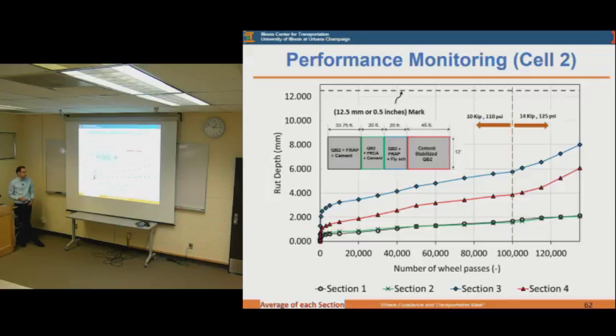And if you can just in particular pay attention to these 2 test sections here, the lowest 2, which are the ones that have the RAP or the RCA mixed with cement. And these were showing very superior performance. They only accumulated less than 2 millimeter of rutting after 135,000 passes. The section that had the worst performance, which still performed very, very good, like 8 millimeters only of rutting after 135,000 passes, is much lower than what our target was of half an inch of rutting.